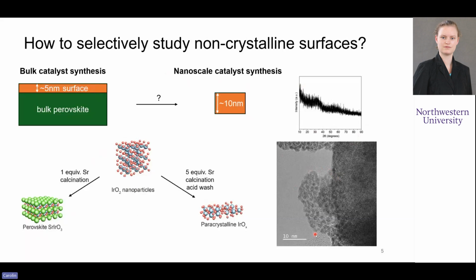And when you look at it in the TEM, you can see the nanoparticle region here that is not crystalline. It's also not amorphous. It looks almost glassy. And so that's a really interesting material to study. And so we then went ahead and took a look at what we can learn about the structural motifs that are present in this nanoscale catalyst material, and how we can compare that to the perovskite.